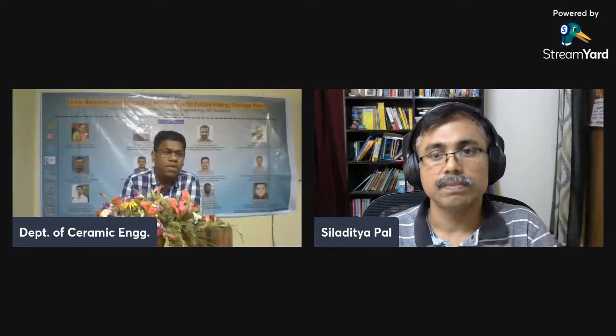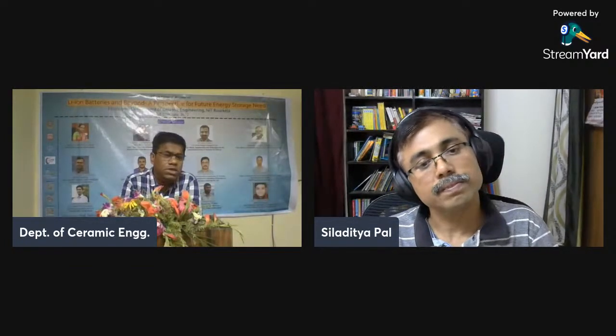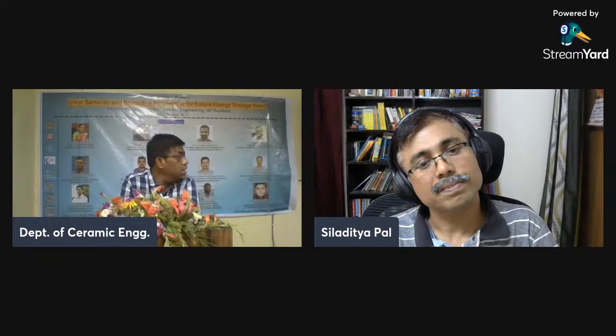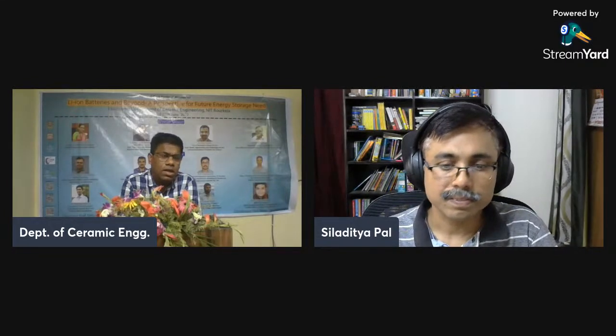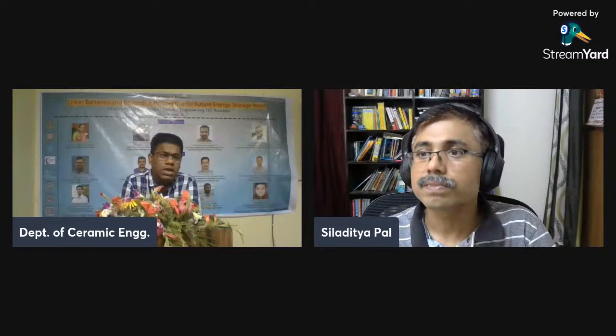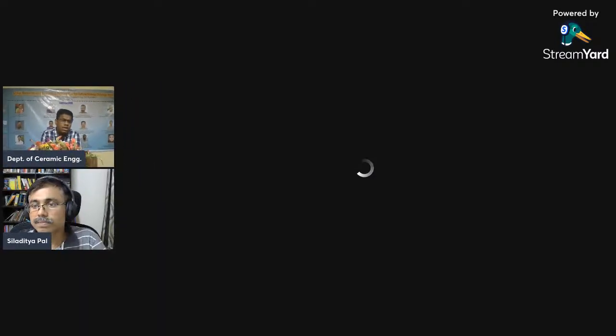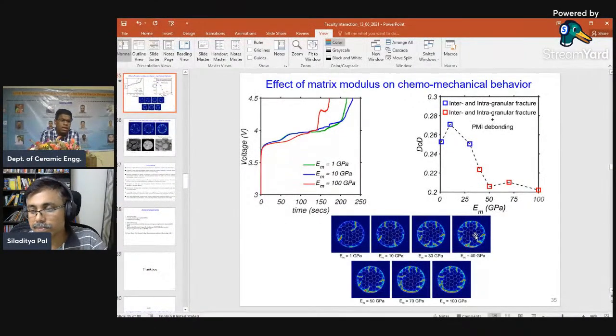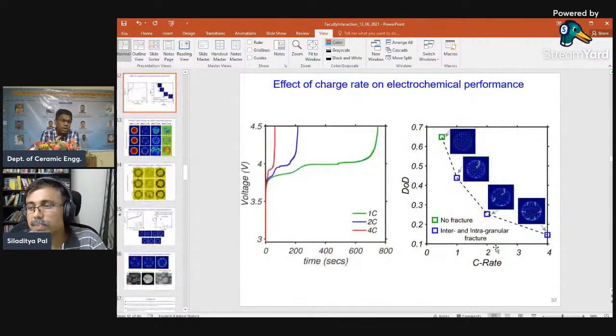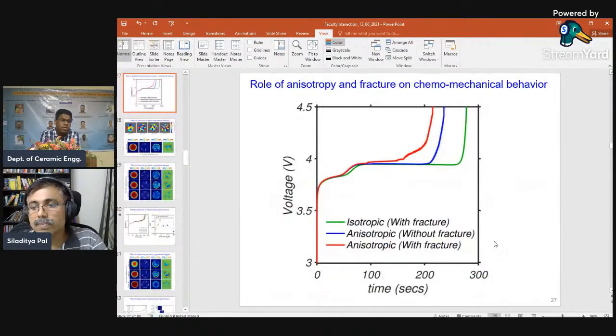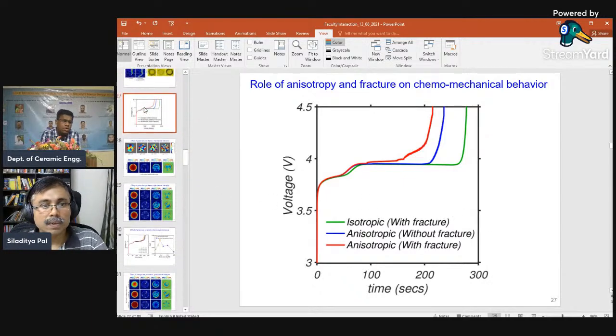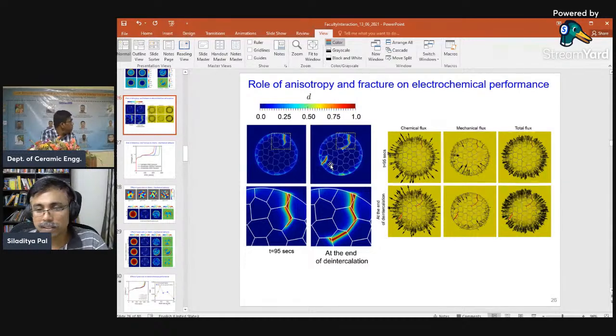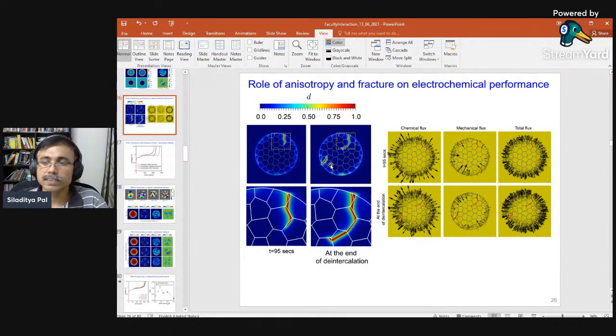Okay, thank you. And my last question to you, actually, this is my curiosity. If you look at your slide numbers 26 and 27, you have mentioned that the surface cracks are generated during the intercalation, so that is the discharge cycle. But on the next slide, when you plot the anisotropic and isotropic failure, you are showing voltage versus time on the charge cycle, whereas in the previous slide you showed fracture originating during the intercalation. So can you tell us the reason? Here you are talking about this one, 26.